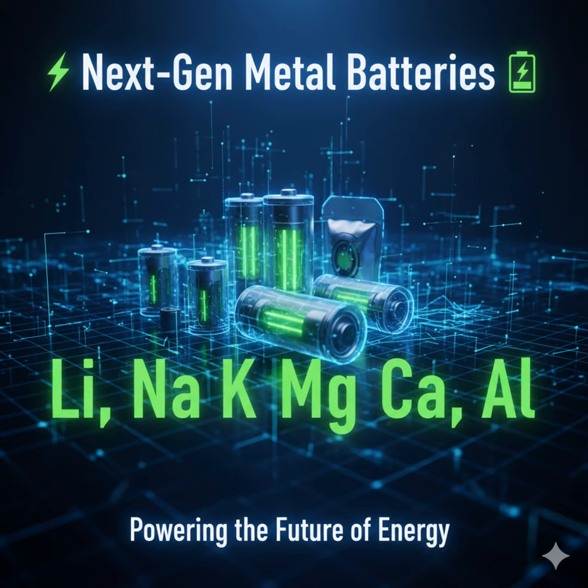No. And this is a key difference. The monovalent metals, lithium, sodium, potassium, they tend to grow these really aggressive, nasty shapes. The paper calls them whisker-like, moss-like, and tree-like dendrites. Tree-like, little metal trees growing inside my battery? Pretty much. They branch out, they reach far. Think of them as the vicious vines, just snaking their way towards that separator, ready to cause trouble.